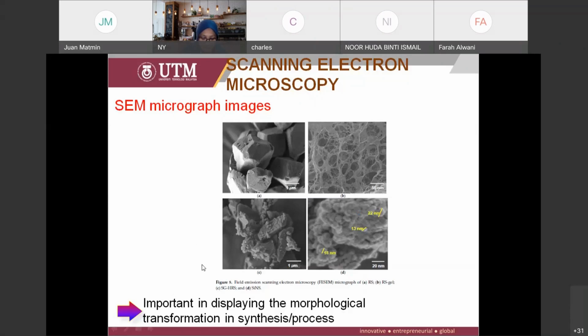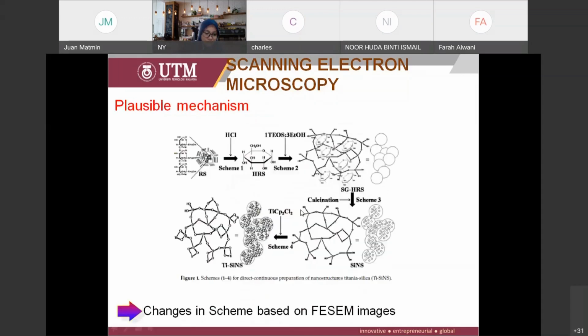Okay, so this is the contribution of SEM in displaying the morphological synthesis. We can not only have a simple micrograph image of a final product, but we can follow the transformation of a synthetic process, a new process that we propose. So in this paper, we also proposed a plausible mechanism of how the rice starch acts as the template in the new protocol here, and this follows the SEM images that we measured.